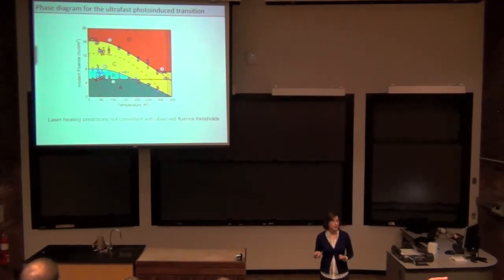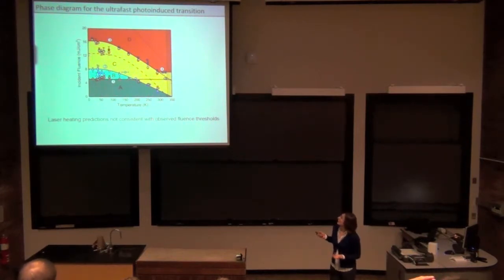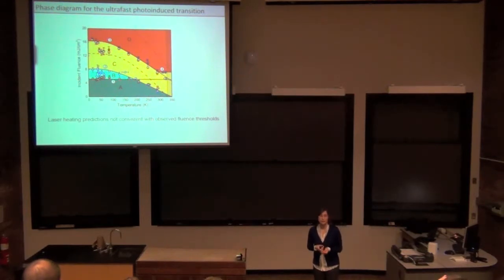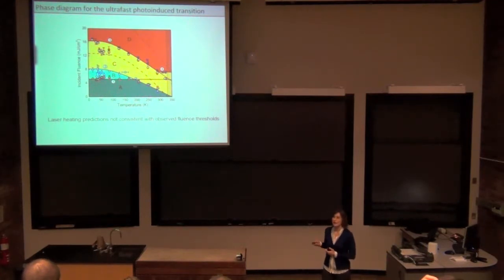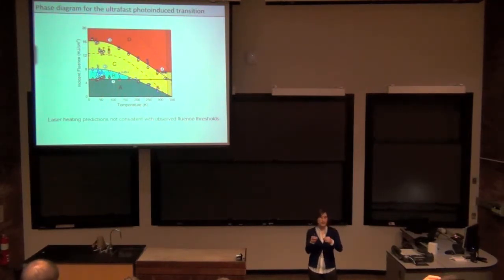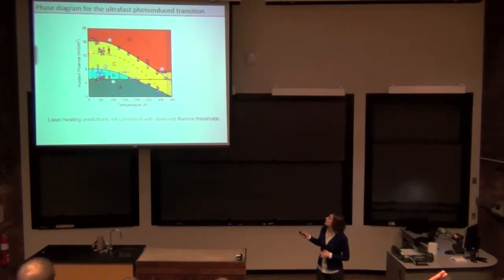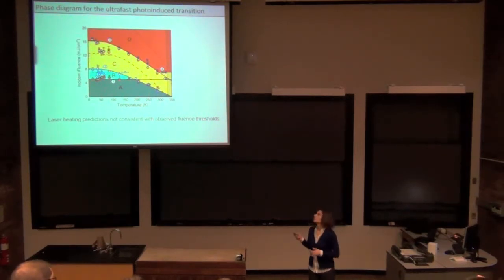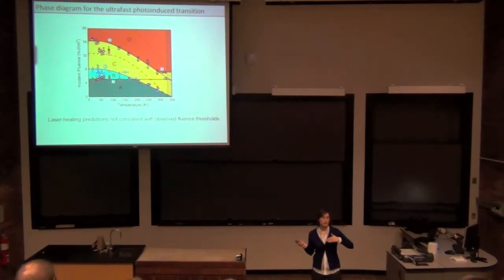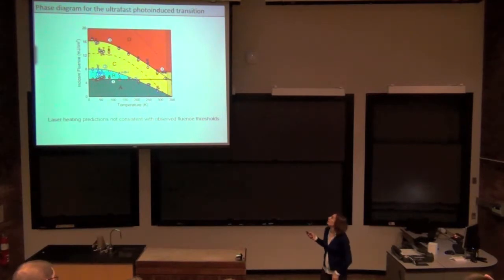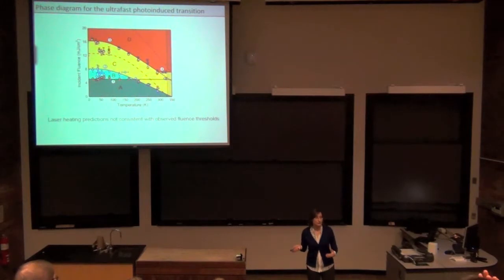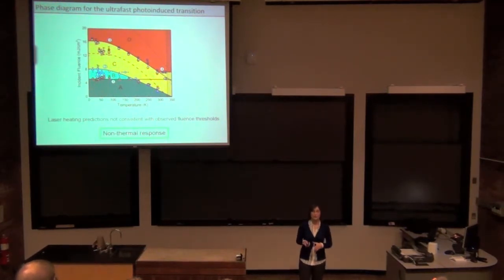The first question that we wanted to ask ourselves was, is this transition thermal? For that, we know the thermal properties of the material. We know the heat capacity, the latent heat, and all things like that. So we can actually calculate how much fluence we need to heat, for example, just the top layer of the sample to the onset of this metallic transition, just to start it. And that was this curve. Then we can calculate how much fluence we would need to bring the average sample temperature to the transition temperature, where the film would be switched. And that is this curve. And then finally, to heat the back side of the sample above the transition temperature, that would be this. Of course, what we have seen experimentally, the threshold is significantly lower than those predictions. So that tells us that the ultrafast response is non-thermal in nature.